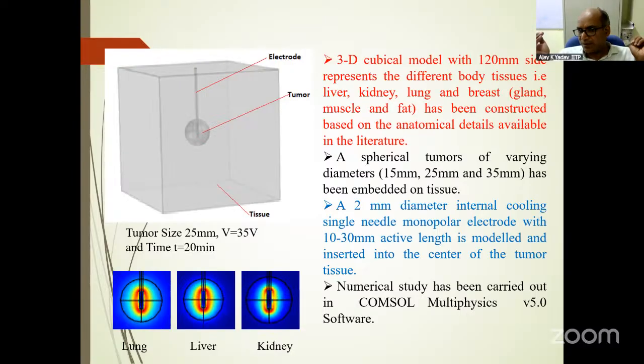Beyond 3 centimeters, it is difficult to treat using these techniques. In that case we can use some nanoparticles so that we can get a homogeneous temperature distribution, by increasing the effective conductivity of the tumor tissue, because we are injecting nanoparticles into it. So there are 3 studies here, and the electrode we are going to insert is a 2 mm diameter electrode. You can see the electrode here.